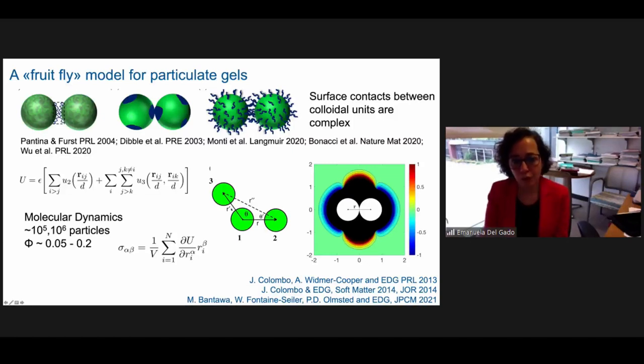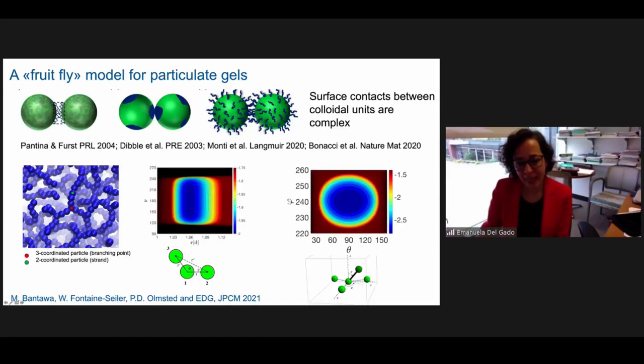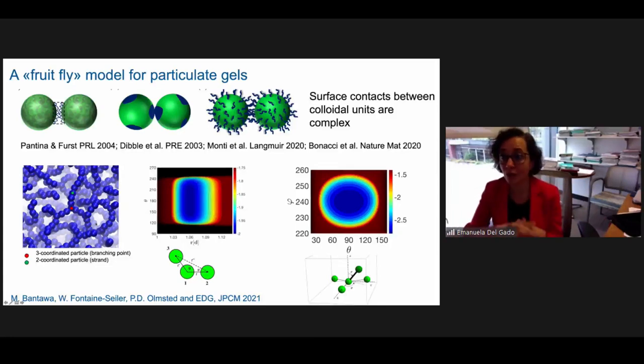this leads to the formation of a gel network with a number of different gelation protocols that we have tried, that basically has a structure that is relatively simple, where we can identify two structural elements. So either particles are basically forming one particle thick strands, so these gel strands that you can see here, and then these gel strands branch and connect to form these larger scale networks. So these branching points are, of course, very important for the frustration, for the development of the frustration that I was discussing before, but not only.